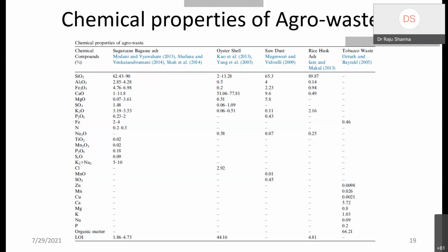And when you do the analysis, you can look at the element distribution through the mapping of the microstructure, and there you can find the chemical ratio as well by doing EDS on different locations of the paste. By doing so, you can qualitatively conclude that a phase occurs where the Ca/Si ratio is something different, meaning somewhere it is 1, somewhere it is 1.5 or something like that. In many research papers, you can see this statement which we are discussing here.